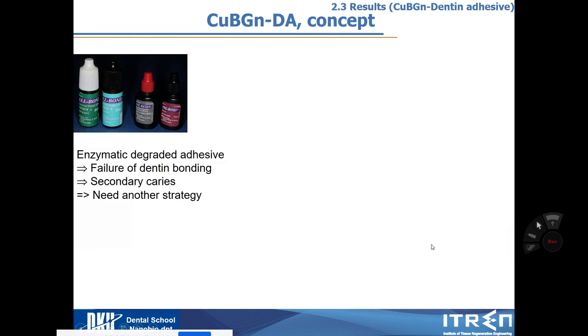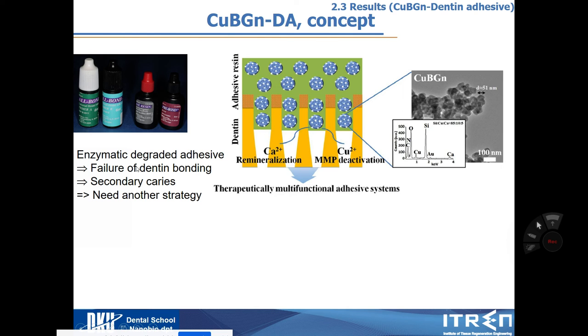And as a last topic, when you want to make a bond between dentin and composite resin, we need a dentin bonding agent. But sometimes, from enzyme degradation, they induce failure of dentin bonding, and they cause secondary caries and need another strategy to overcome this enzyme degradation of the dentin bonding. So here, to decrease enzymatic potential from the dentinal fluid, I incorporate copper BGN, copper incorporated bioglass, in the dentin bonding agent to make a therapeutic adhesive system.